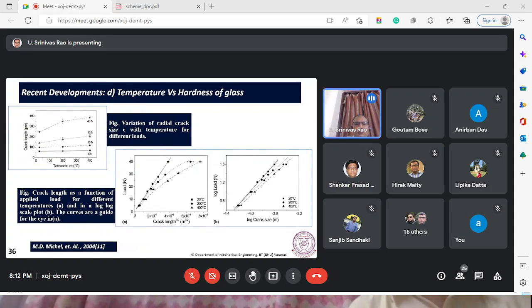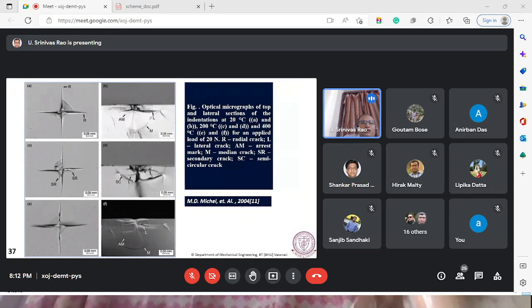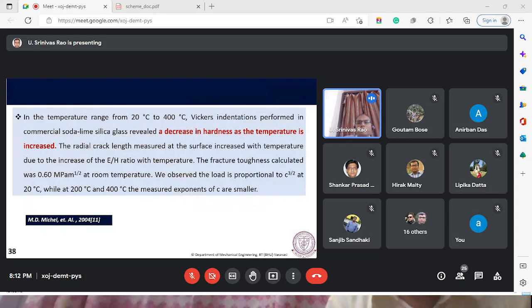So when you increase the load, crack length increases. Of course, that is quite obvious. And with increasing temperature, at different loads, the crack length growth is less. So from these experiments, extensive experimentation, these are the conclusions, which are of course obvious. The only thing is that we need to find out what is the nature of the change, at what rate the hardness is decreasing as the temperature is increased.